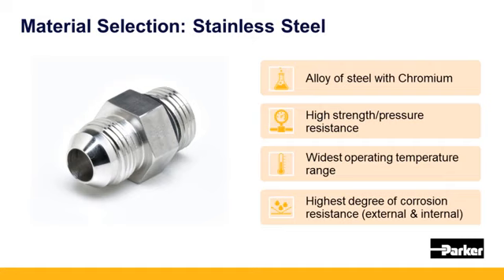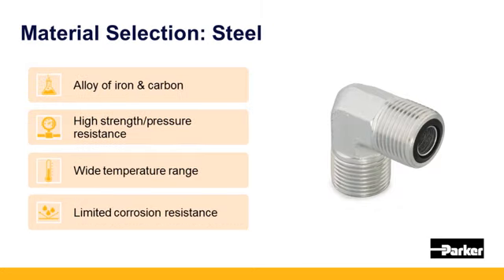It's often the default choice for aggressive applications where the media or surrounding environment is corrosive. Good resistance to acids as well if your equipment might be exposed to that. Very high pressure rating, equivalent or comparable or even sometimes higher depending on the grade than carbon steel. Good temperature range as well. However, the offset to that, of course, is that stainless steel is not as commercially viable because of availability, and it's significantly more expensive.